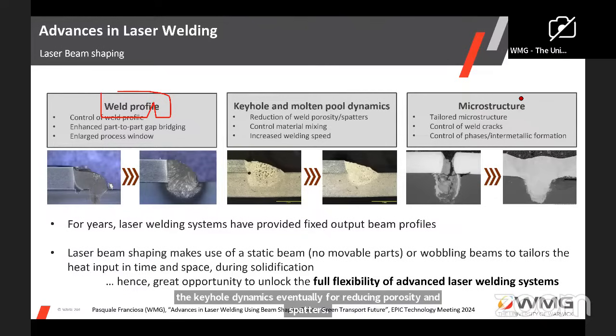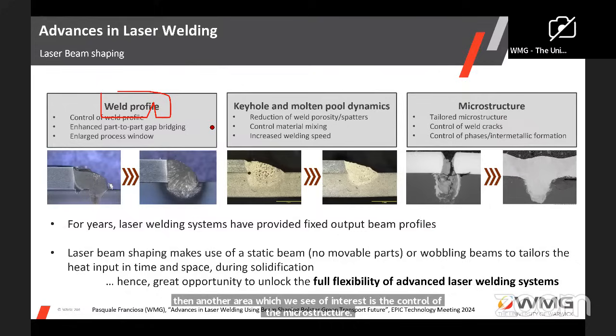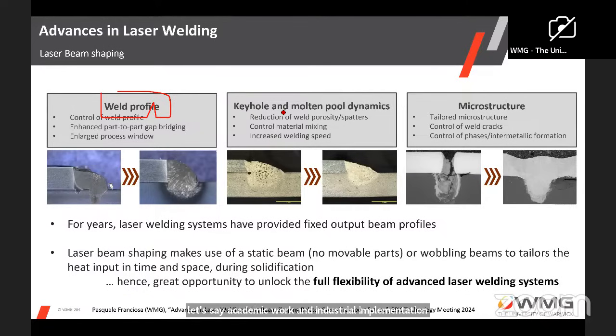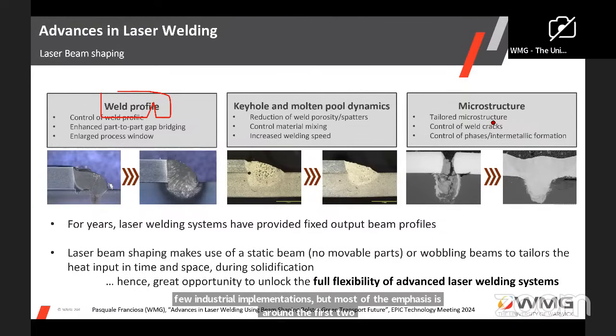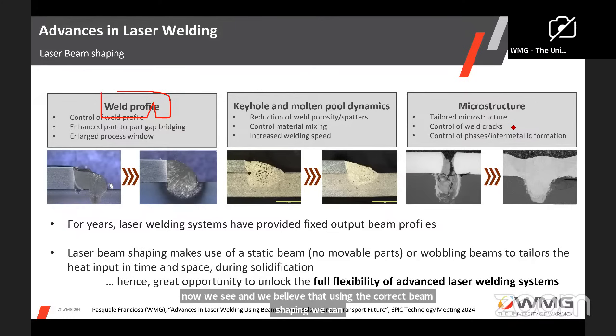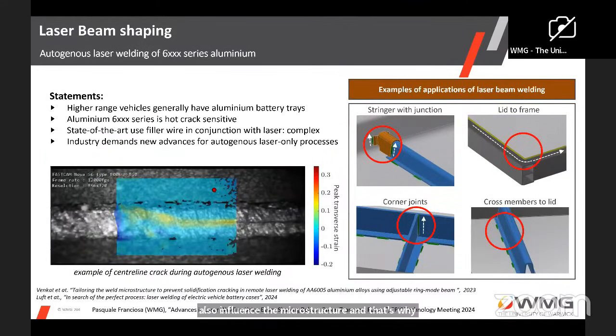And then another area which we see of interest is the control of the microstructure. Now, statistically speaking, there is a lot of academic work and industrial implementation between the first two areas, so weld profile and molten pool dynamics. There is very little on using beam shaping for controlling the microstructure. Now, there are some academic contributions. Probably there are a few industrial implementations, but most of the emphasis is around the first two. So now we see and we believe that using the correct beam shaping, we can also influence the microstructure, and that's why we have been investing time and effort in doing that.